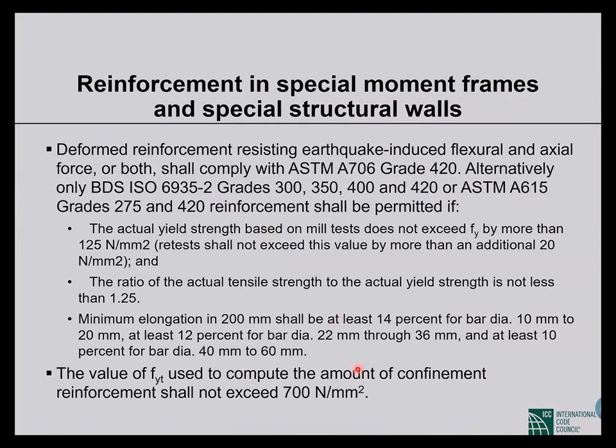More restrictions for special moment frames and special structural walls. The code has these provisions. Number one, deformed reinforcement resisting earthquake-induced flexural and axial force, or flexural or axial force, or both, shall comply with ASTM A706 grade 420. Here, you see, previously we talked about ASTM A615. So this is another new standard, ASTM A706.